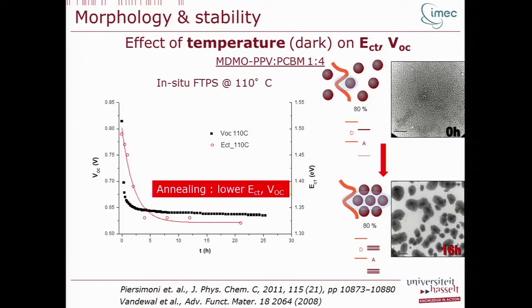And what we have provided as an interpretation for this fact is that if you have this phase separation, you have more ordering occurring, and when you have more ordering, you have more band broadening, and your effective band gap becomes smaller. So temperature has an effect on morphology and affects also the ECT and the VOC.